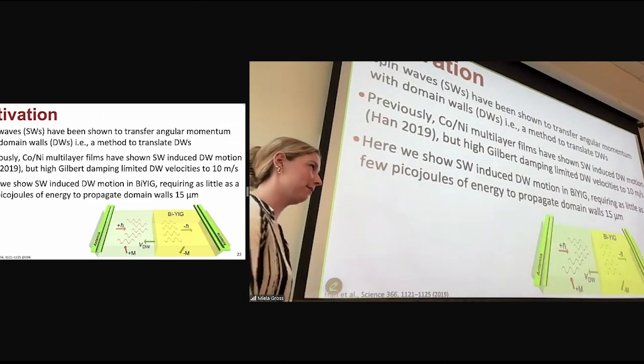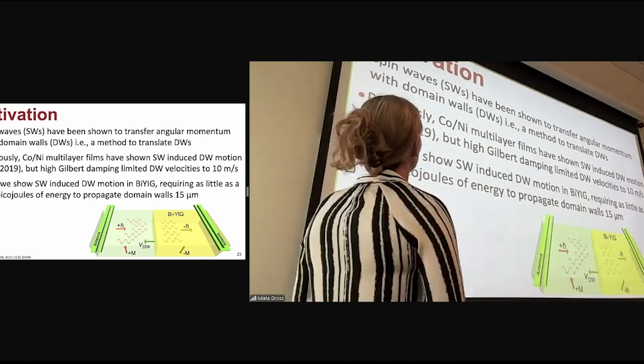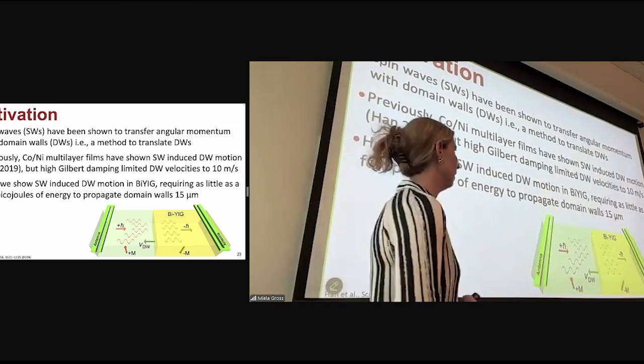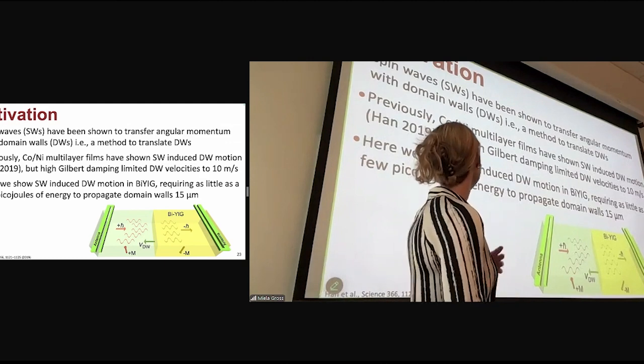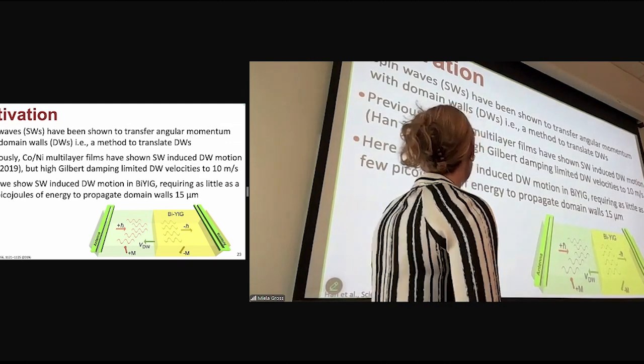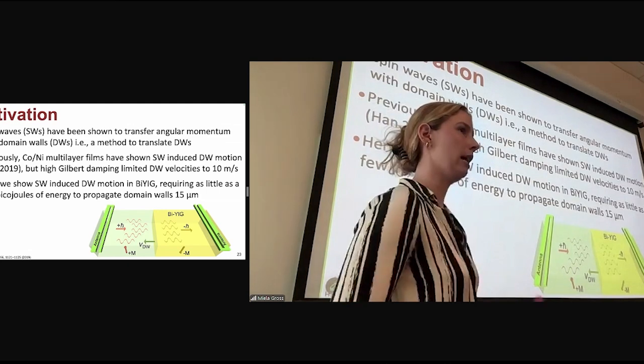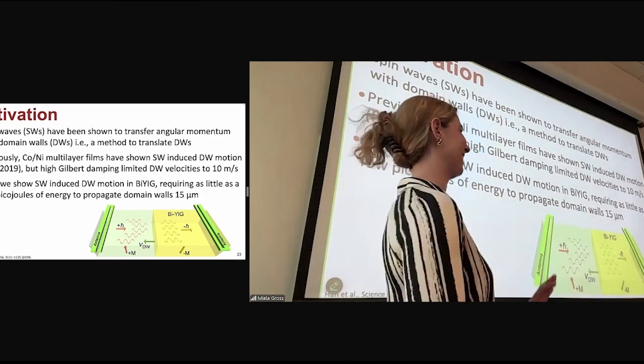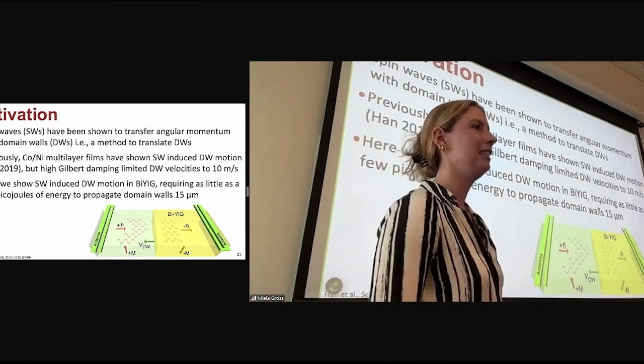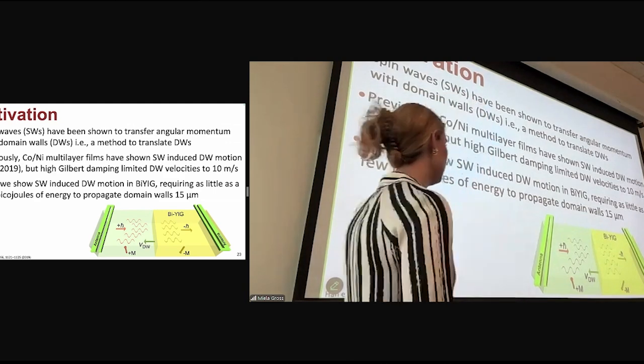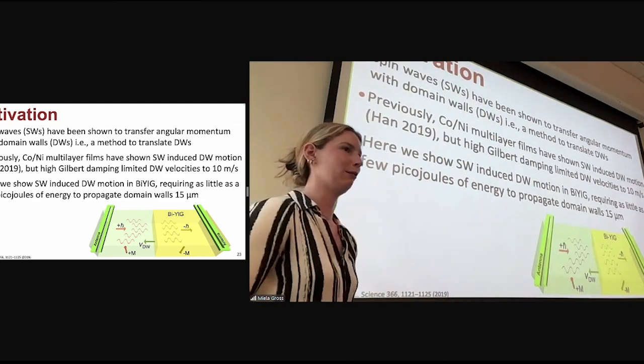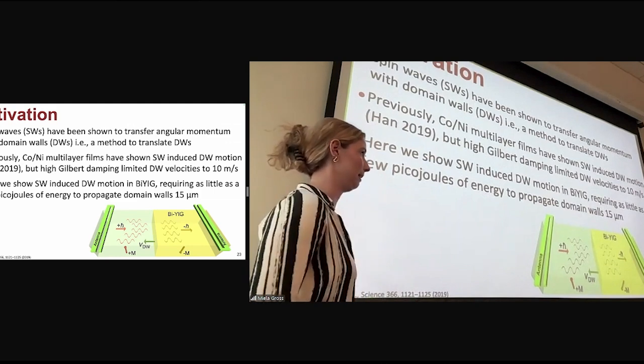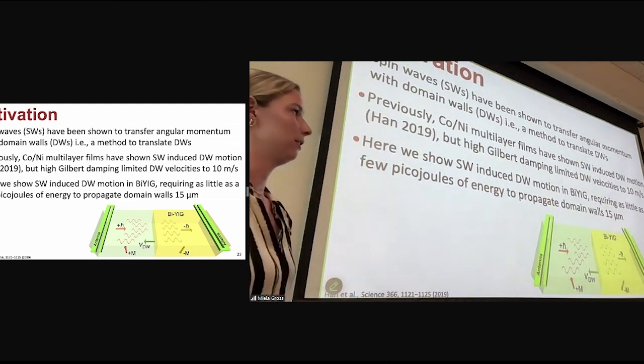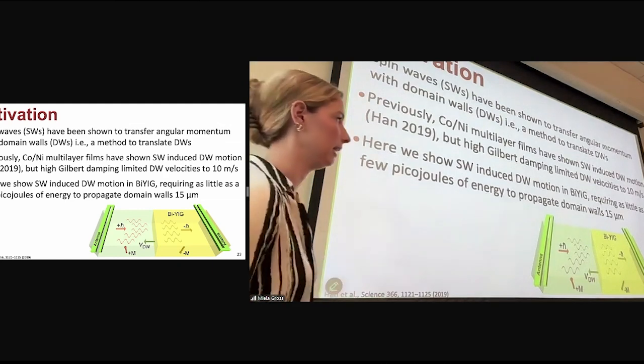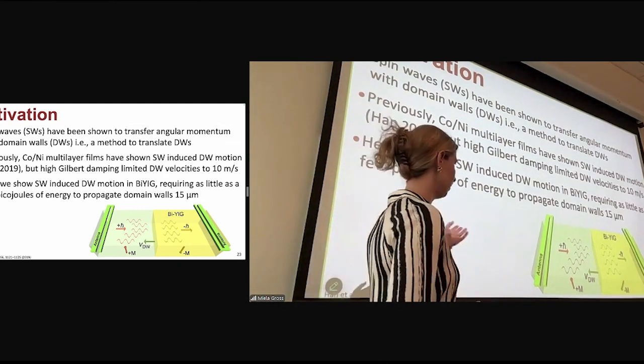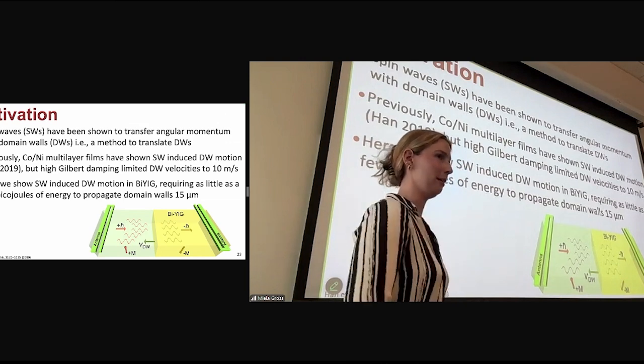So spin waves have been shown to translate angular momentum with domain walls as a method to move them. This has been shown previously in cobalt nickel multilayer films. However, the high Gilbert damping of these magnetic conductors limits domain wall velocities to only 10 meters per second. As I mentioned, in some of our garnets, we can have really high domain wall velocities because of that low Gilbert damping. So here we showed spin wave induced domain wall motion in bismuth substituted YIG, which requires as little as a few picojoules of energy to propagate domain walls up to 15 microns.